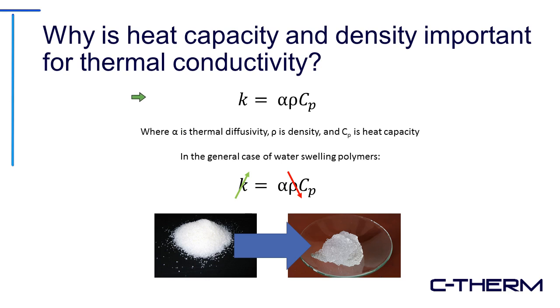But what else can we do with these polymer type of materials? One thing that's really important is to look at the heat capacity and the density in this formula. Thermal conductivity is equal to the thermal diffusivity times the density of the material times the heat capacity. So in general, we can affect the thermal conductivity of a polymer by changing density and the heat capacity of the material. In the general case, when we have a dry polymer, which is sodium polyacrylate, versus a wet polymer, when we swell these types of polymers in a biological system, we can effectively lower density and CP and increase its thermal conductivity.